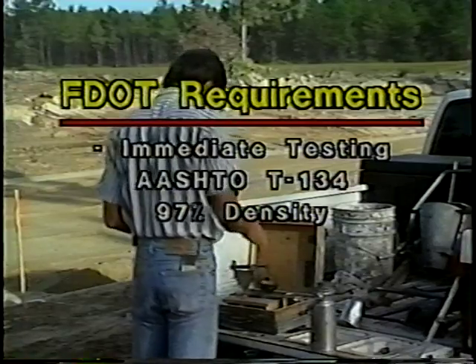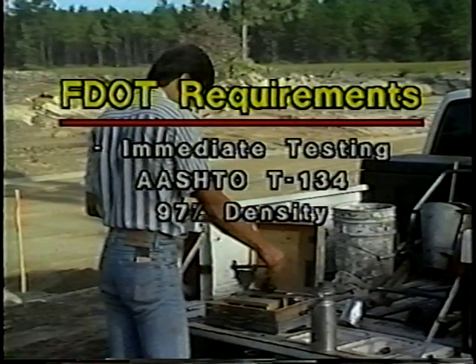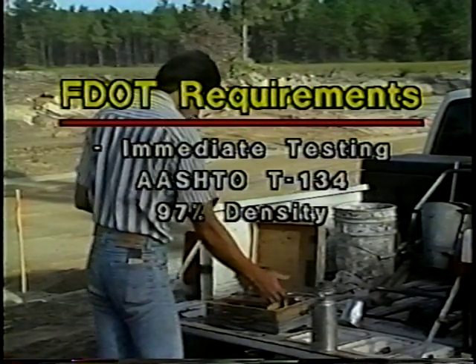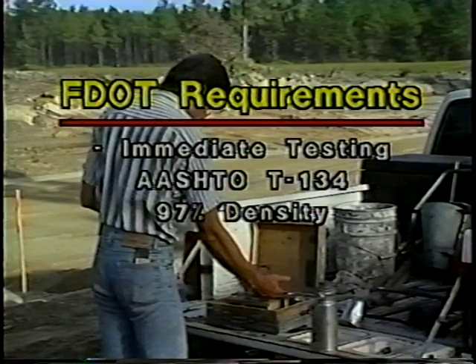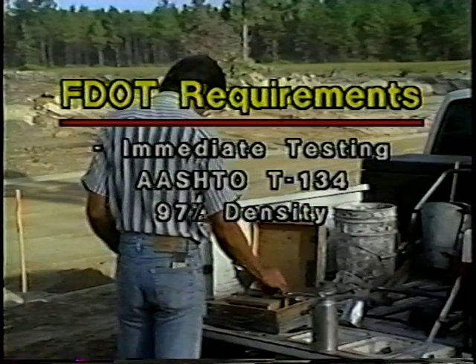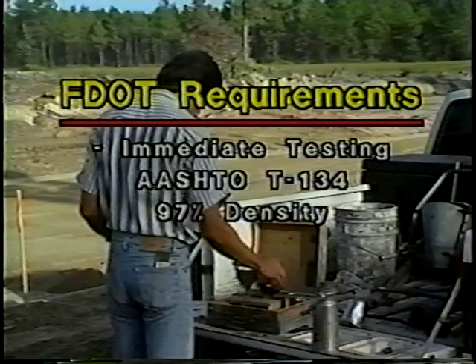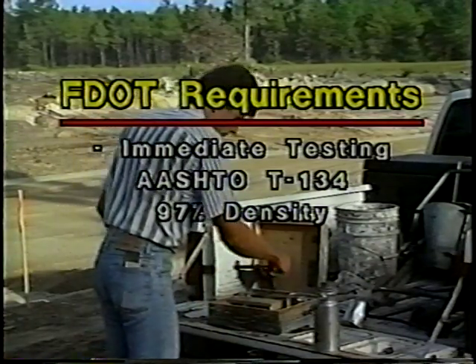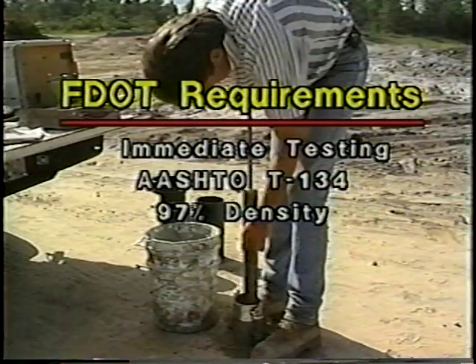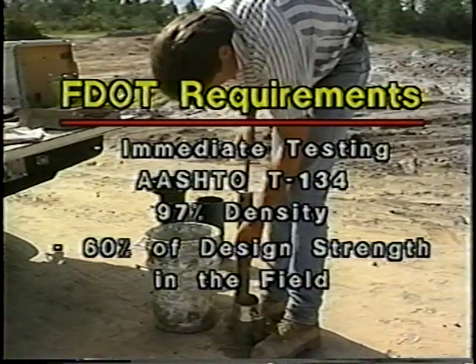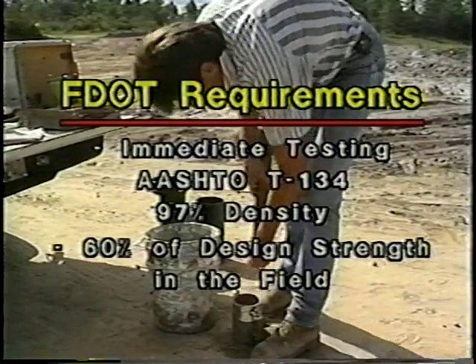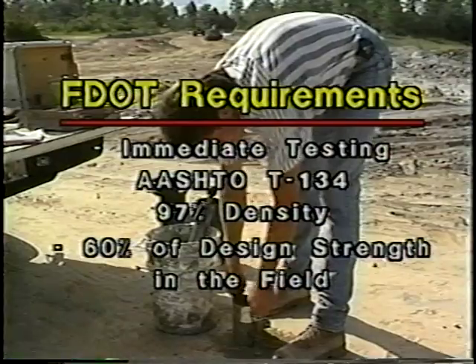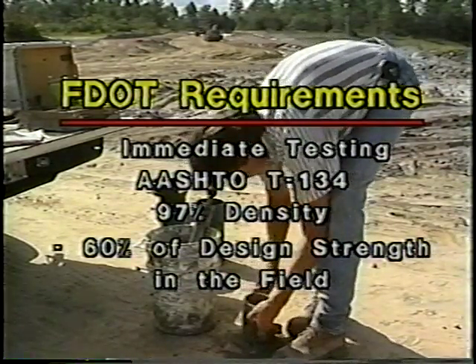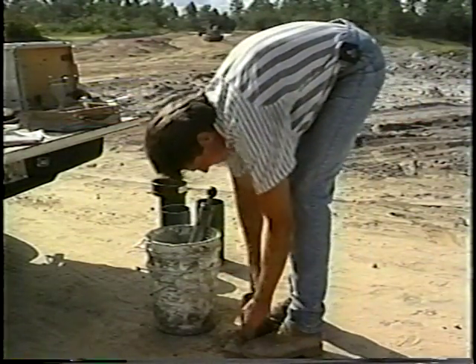The FDOT specification requires immediate testing for field density as soon as possible after completion of compaction, using the methods prescribed in AASHTO T134, with the required density of at least 97% of the maximum. In addition, for mixed designs accomplished by the strength design method, field strengths of 60% of the design are accepted for quality assurance. No strength tests are taken for mixes designed by the brush loss method.